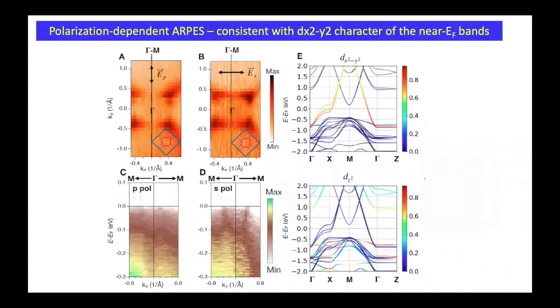I can do symmetry analysis by varying my photon polarization from P to S. There's details about this using mirror planes and whatnot. The upshot is you find that this is dominated by the dx²−y² states, and then also what the DFT shows.